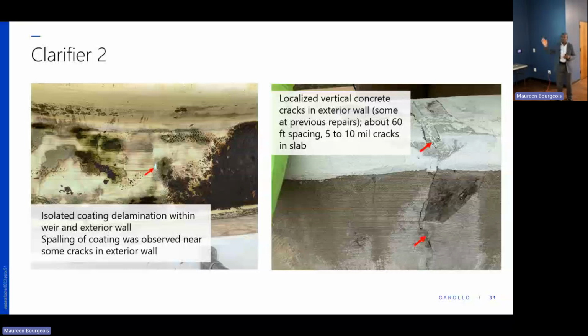Again, it's well above the 4,000 mark, which is on the drawings. In this case, we're in the 5,000 to 8,000 range of all the cores that we tested. So the structure is structurally sound. Carbonation depth 0.13 inches, also less when we think about the cover, so we have enough. And then the chlorides are also below the 350 parts per million, and so it's considered negligible risk.